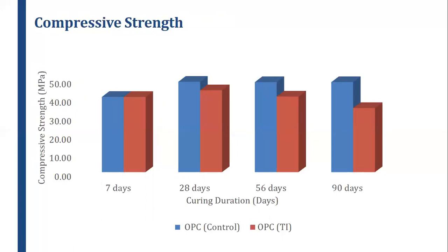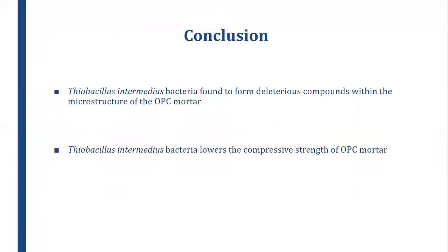This again was linked with the influence of the bacteria on the cement, and it was clearly indicated that this bacteria affected the mechanical property of the cement, that is the compressive strength. From this work, we were able to conclude that the Thiobacillus intermedius indeed resulted in formation of deleterious compounds within the microstructure of the OPC mortar. This bacteria lowers the compressive strength of the OPC mortar as well.